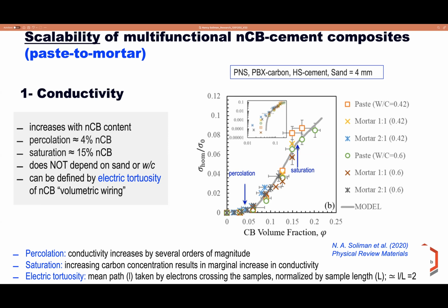And what we see here is that this figure shows the tortuosity-based model performance, which shows the normalized electrical conductivity, measured electrical conductivity normalized to the electrical conductivity of pure nanocarbon black, versus nanocarbon black volume fraction, and modeling for that. For all the samples considered, and the inset of the model here is the performance in the log scale. And it can be observed here that the electrical conductivity of all cement pastes and mortars collapses into one curve,